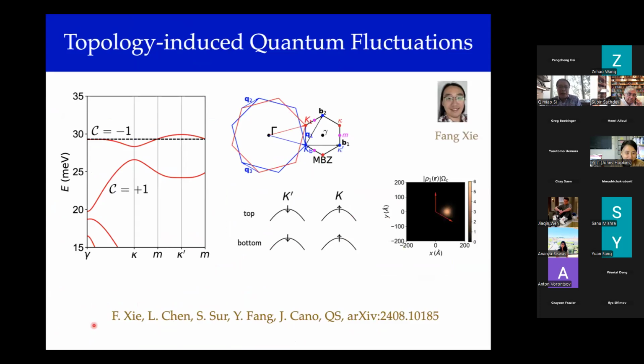So here I want to use that as a guide to think about the flat band in combination with nearby wide bands. In fact, if one does a reasonable estimate of interactions, it would be mixing the flat band with the adjacent wider bands. And it is not entirely clear. We know the bands are topological, but precisely this true number for particular value C equal to -1, whether it's accompanied by -1 or +1 for the nearby band, depends on the choice of the moiré potentials. So we'll work in a regime where the spin Chern number, the valley Chern number, has opposite values from the two bands, and it turns out that in this regime one can construct these molecular orbitals. Some of them are closer to half filling, and the others are far away from half filling.